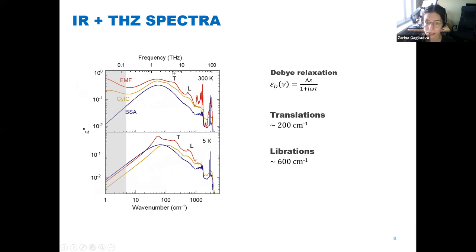And the existence of conductivity also correlated with the existence of translational and librational lines of water molecules in the infrared region at about 200 and 600 reciprocal centimeters. So this gave us an idea of the correlation between bound water response and charge transport existence in our samples. However, the exact ways in which water affects conductivity in these materials, as well as the possible influence of aqueous cations which are formed from water molecules, were not observed.